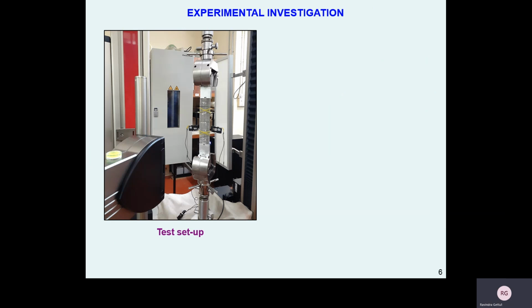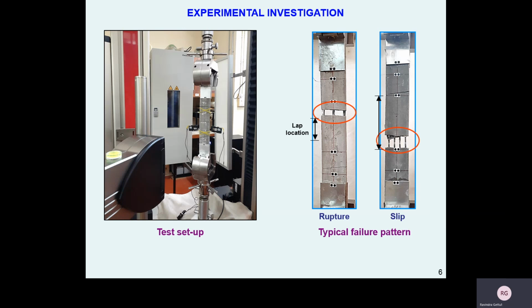The prepared specimens were gripped as shown in the figure in an electromechanical testing machine and subjected to axial tension. Axial extensometers attached to the specimen and a non-contact video extensometer were used to capture the test data. All the specimens were tested. Prominent failure patterns were revealed by the test. One was through rupture of textile at a crack, which showed the intact behavior of the lap, and the other was through slip of textile layers at the spliced region.